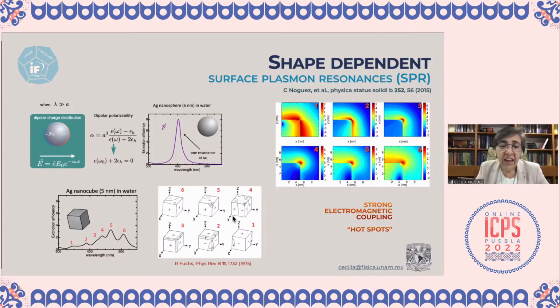And then you will have this kind of resonances. It is very interesting that, for example, we can identify these resonances, these peaks in the spectrum as a function of the wavelength, and also we can look at this near field or near electromagnetic field in each one of these resonances. And you can see, for example, for mode 1, we can enhance up to 3 orders of magnitude the near field electromagnetic field, and it has this distribution along, for example, the cube in this case.